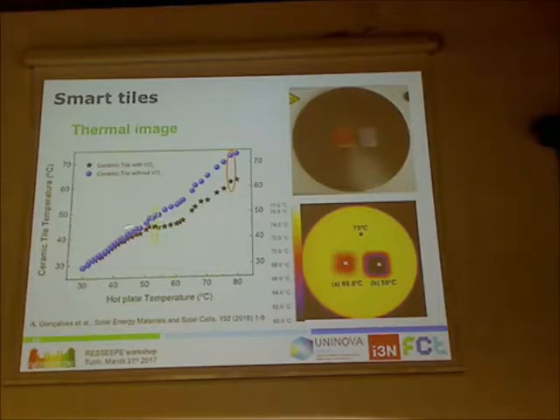This shows the temperature difference between the coated and uncoated tile. They start to differ right around the transition temperature of 45 degrees. The temperature measured on top of the coated tile becomes always lower than the uncoated tile, following the hot plate temperature in a linear relation—but with a shift that happens due to the transformation from non-reflective to infrared reflective. So you measure less temperature on top of the tile.